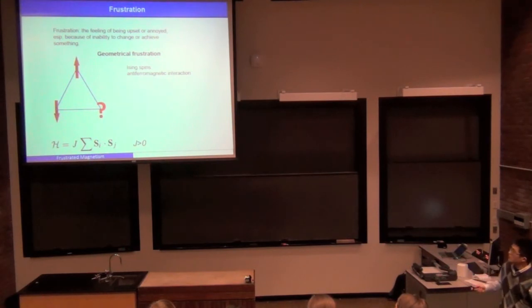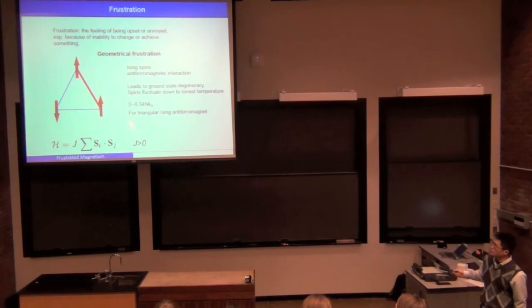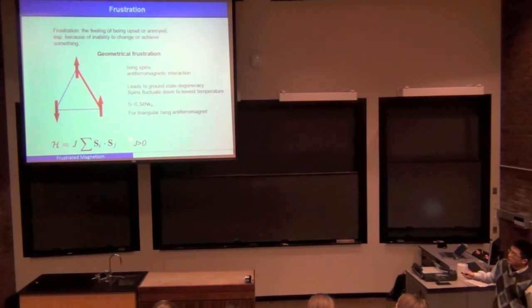It turns out, no matter how you point it, this spin would be unhappy with one of its neighbors. For example, if we point it up, then this bond highlighted in red would be in a higher energy state because it cannot be in antiferromagnetic order with this one. So as a result, this bond is unhappy and costly, so this is frustrated. And the frustration in a magnetic system would lead to ground state degeneracy.